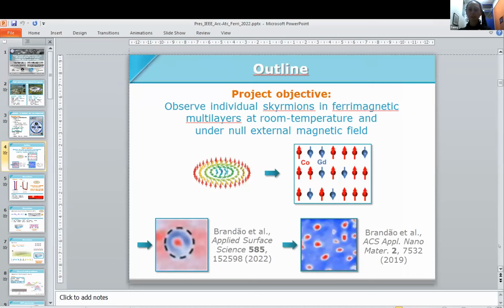In one, we decided to use some lateral confinement to be able to stabilize individual skyrmions. And on the other side, we decided to vary the thickness of the ferrimagnetic multilayer until achieving a thickness where we were able to directly have this stabilization.